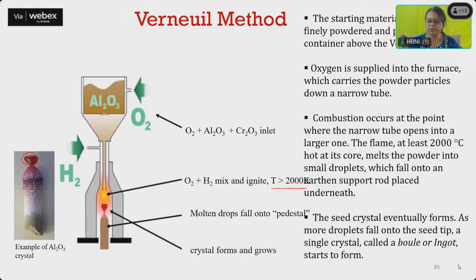So the starting material, that is alumina, Al2O3, is finely powdered and placed in a container. So this is kept here, and this is the furnace part. From one end, he is putting hydrogen, and from the other end, oxygen. And a flame is produced here. Because Al2O3 with chromium is there, it comes flowing down. And the amount of material which is flowing down can be controlled from this orifice. So from here we are controlling the amount of material, like the growth rate.